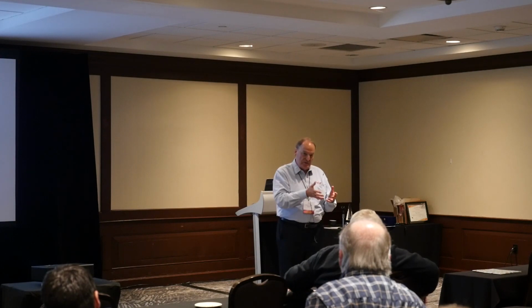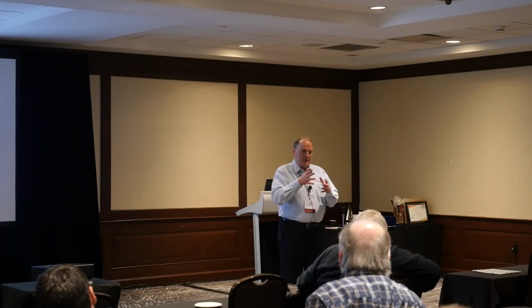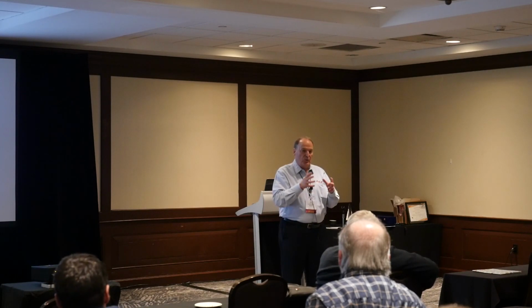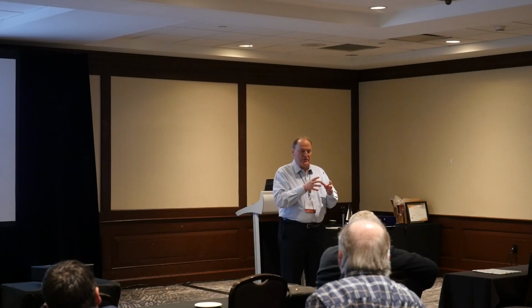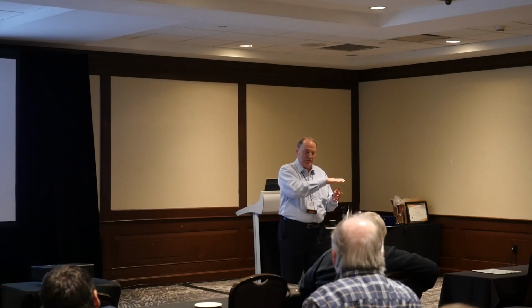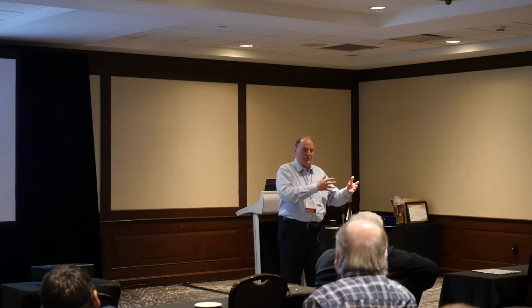The general picture is, as you put a refillable bottle through the filling line the first time, it picks up some damage. That diminishes the strength. As it is continually reused, it gets more and more damaged. In other words, you see more and more of the scuff bands, but the severity of the scuffing is about the same. So the strength plateaus out, even though the appearance gets worse and worse, the strength isn't affected. So when you're doing design work, you know what that asymptotic value is. You design to meet that.